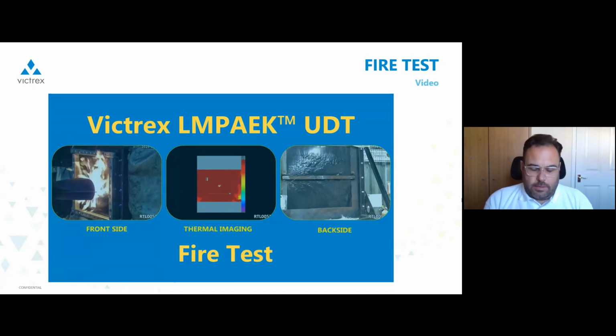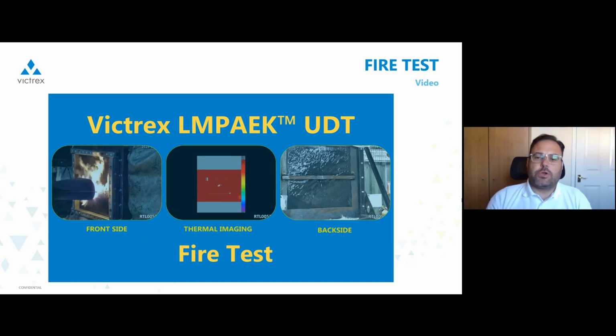attacks the panel. For those that have done fire tests, they will tell you that anything interesting will happen in the first 3, 4, maximum 5 minutes. Usually, in 99% of the cases, if nothing happens in the first 5 minutes, I mean, no fire penetration, no volatiles, no secondary burns, or anything like this, usually the system comes into equilibrium. So this is what we saw here. Again, 15 minutes compressed into 1 minute.